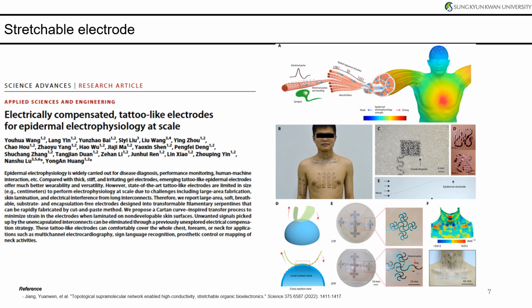Fourth, under harsh conditions, repetitive and strong deformation of the skin occurs, with the maximum skin strain during movement known to be around 40%. To allow the electrode to conform to the movement of the skin without damage or detachment under such harsh conditions, the electrode must be stretchable. This paper created a stretchable electrode using a serpentine structure.